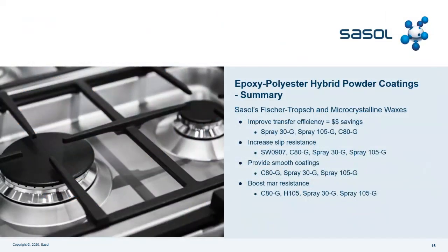Now, this is a summary for you. For epoxy-polyester hybrid powder coating, for improved transfer efficiency, so saving money, we have the best results with Spray 30G, and then the others follow. For increased slip resistance, we have Sasol Wax 0907, the microcrystalline one that we use in pre-extrusion, micronized version, and then follow the other micronized waxes: C80G, Spray 30G, Spray 105G.